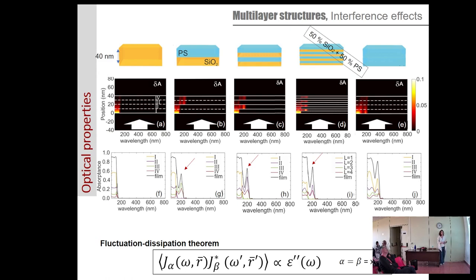just very fast, what we wanted to prove was just to have a look at what was going on with the absorption in this film. So this is a cross section, a profile for bulk silica and polystyrene, and we can observe this is the differential absorption. And this is where the silica absorbs, this is where the polystyrene absorbs, and then due to the interference effects, these hotspots are interchanging here. And if we compute the absorption of the whole film in black here, we can observe that we are really changing and modifying the absorption properties of our system, right?